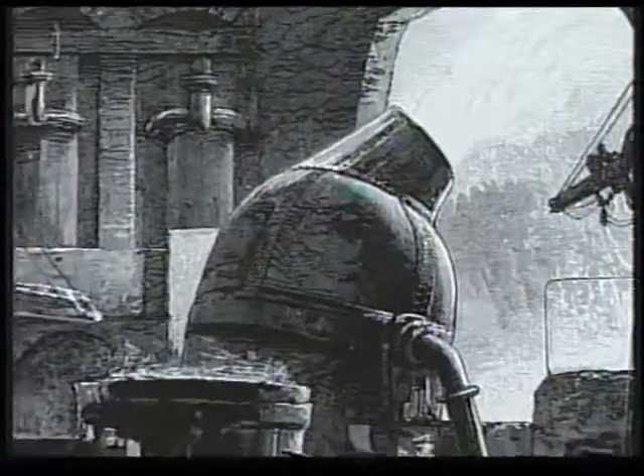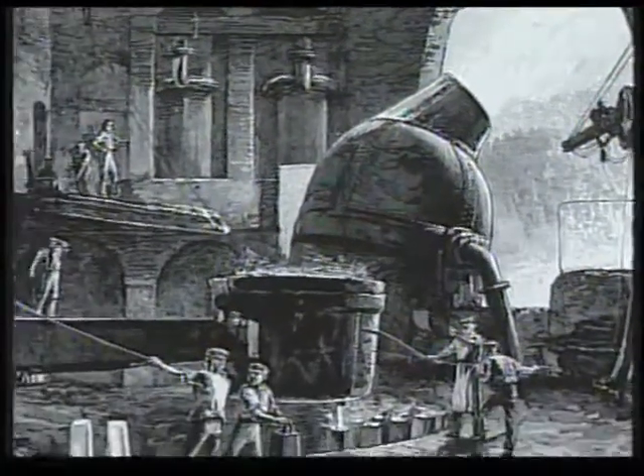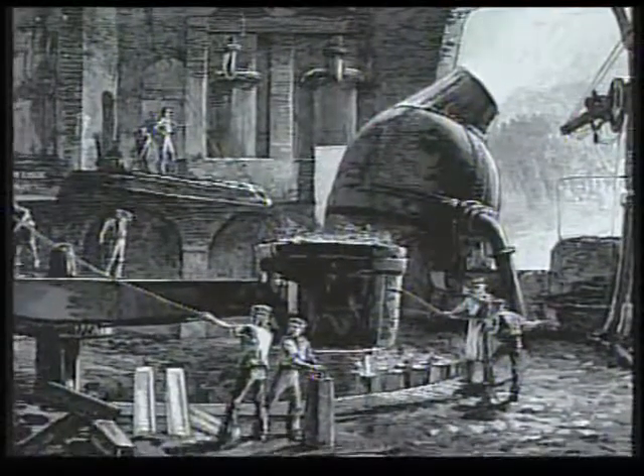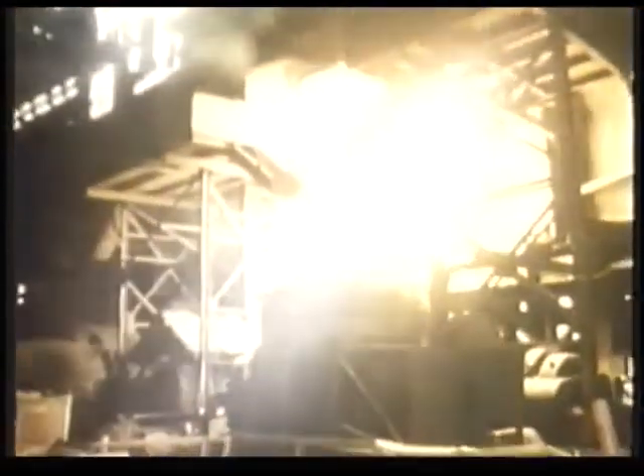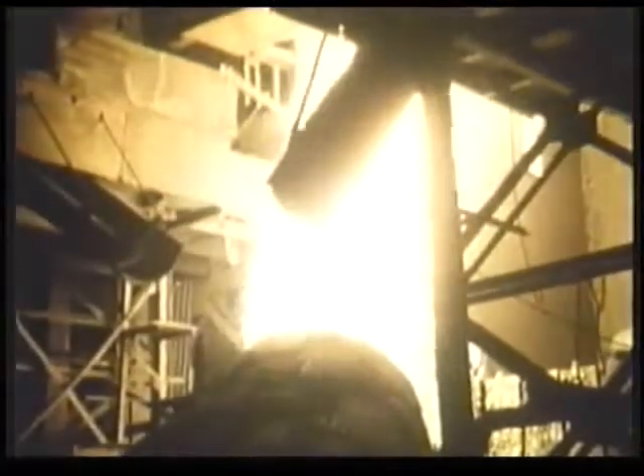In 1856, Henry Bessemer patented a process which at first sight does the craziest thing: blowing air through molten iron to oxidize the impurities. Fortunately, all these burn off during the 20-minute blow, with only partial oxidation of the metal. So, at the end, iron containing carbon is added to reduce the oxidized iron back to the metal in a reaction more reminiscent of what goes on in the blast furnace.